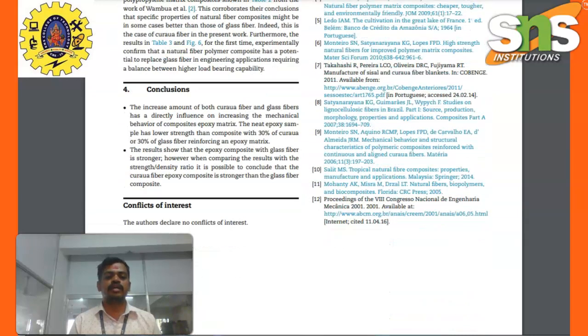The conclusion of this case study is that increasing the amount of both curaua fibers and glass fibers has a direct influence on increasing the mechanical behavior of composites in epoxy matrix. The neat sample has a lower strength than composites with 30% curaua fibers and 30% glass fiber reinforced epoxy matrix. The results show that the epoxy composite with the glass fiber is stronger. However, when comparing the results with the strength and density ratio, it is possible to conclude that the curaua fiber epoxy composite is stronger than glass fiber composites.